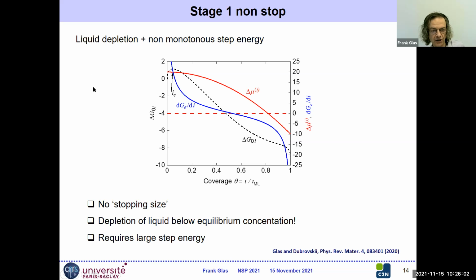So let's now take into account liquid depletion when we grow the monolayer, so decrease of the chemical potential as before, the red curve. And now let us consider the non-monotonous step energy. So at the beginning, we have something which looks like what we had before. The derivative is positive and large, but at some point the derivative will cancel and will go to minus infinity there. So before we had nucleation, this intersection between the two curves, which is still there, but we had the second intersection at the stopping size, where again the delta mu of the depleted liquid was getting equal to the derivative of the energy of the step. And now it may happen, because in this part of the coverage the step energy will decrease very fast, that we don't have this second intersection.